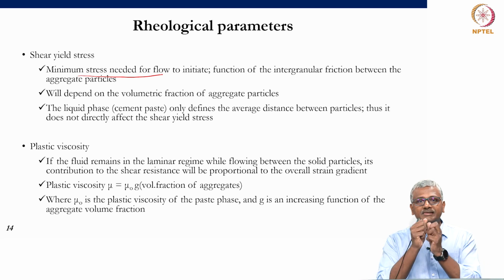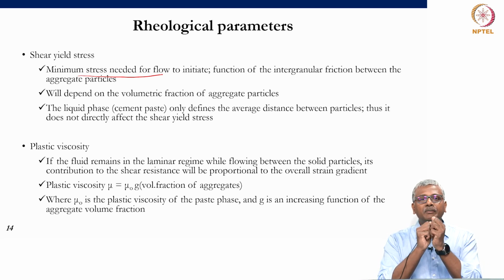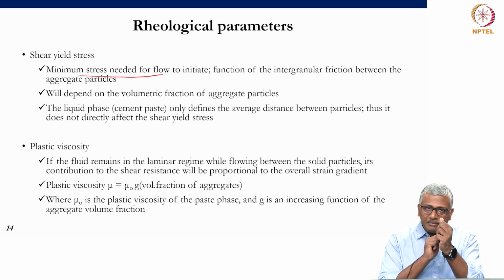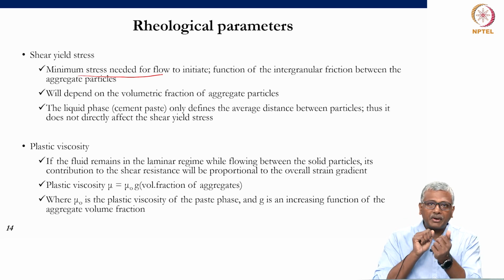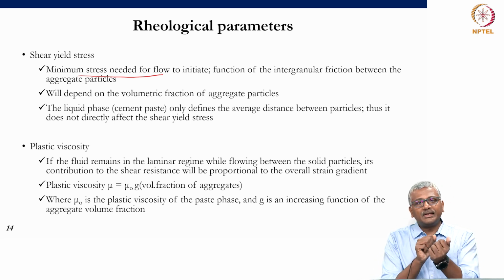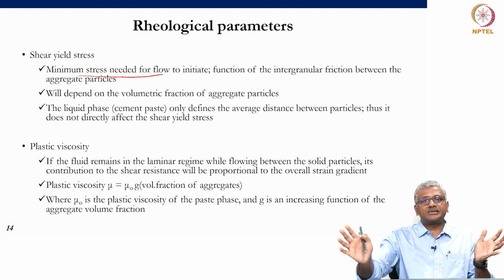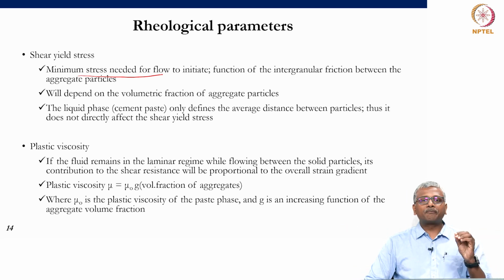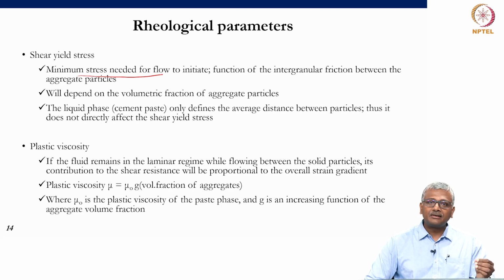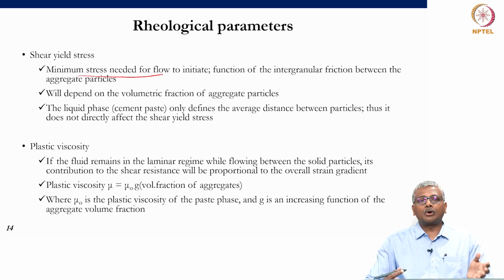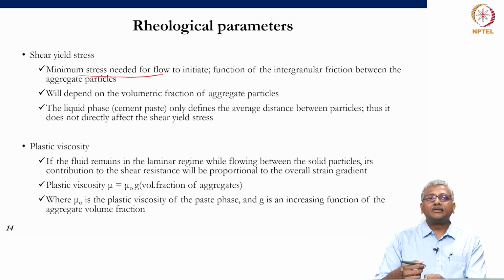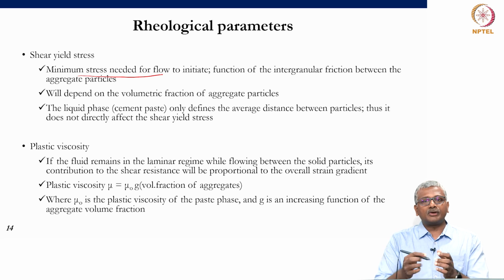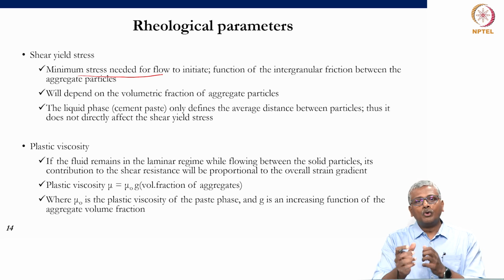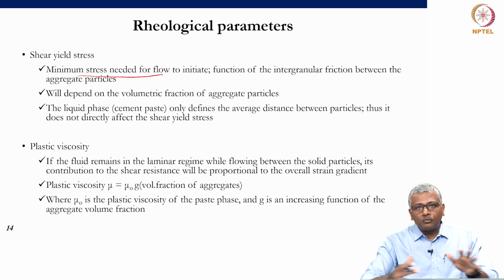So, if there are a lot of aggregates, the aggregates are going to be close together and they will be brushing past each other. To really make them move past each other, you need to apply some level of shear. Only then they will completely move past each other, then the system will start flowing. Okay. So, this is the physical meaning. For instance, when you put concrete into a formwork, it just remains there. But when you put the vibrator inside, the vibration basically causes the aggregate particles to start moving, makes it mobile, and that's what gets the concrete to start getting compacted.